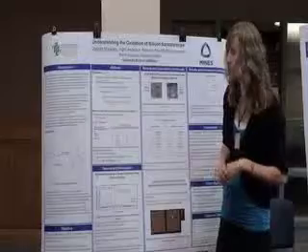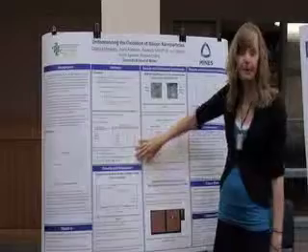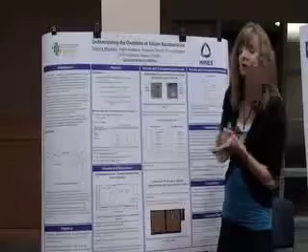And I also changed the oxidizing agent. So there's a lot of ways that a silicon nanoparticle can oxidize. One of those being air, the solvents, water, nitric acid, or a combination of nitric and hydrofluoric acid. At each step of the process, both before and after oxidation, as well as after silanization, I did various analysis techniques: photoluminescence, AFM, or atomic force microscopy, and Fourier transform infrared spectroscopy.